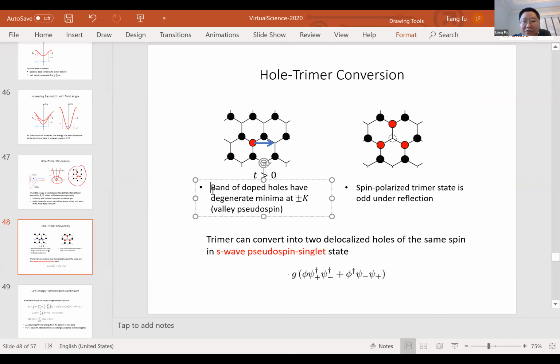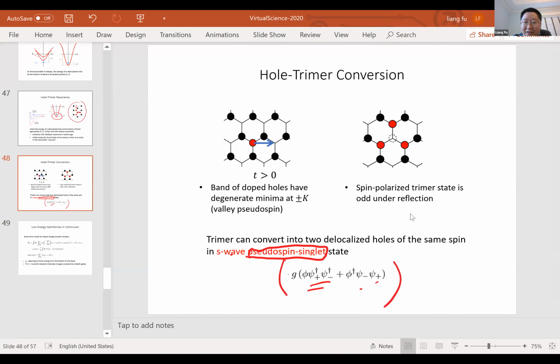So this band of doped holes actually has two degenerate minima at K and K prime points. We can call this a valley pseudospin, and the conversion between the trimers and these two itinerant holes has this form that's dictated by symmetry. So plus and minus denotes the holes at two band minima, plus K and minus K. So this pairing is valley singlet, in the s-wave channel. Again, this is dictated by the symmetry. Let me skip the details for now.